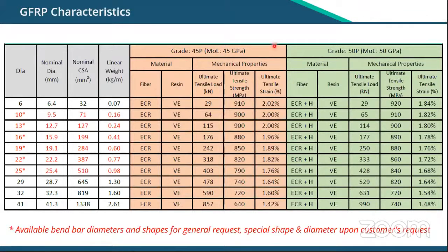At Dextra, we promote mostly two grades for permanent application. One grade that we call 45P, so it's a modulus of elasticity of 45 and P for permanence. We have another grade 50P, so 50 for, again, the modulus of elasticity and P for permanence. But actually we go up to 60. This is less common, but we can offer 60 GPa.